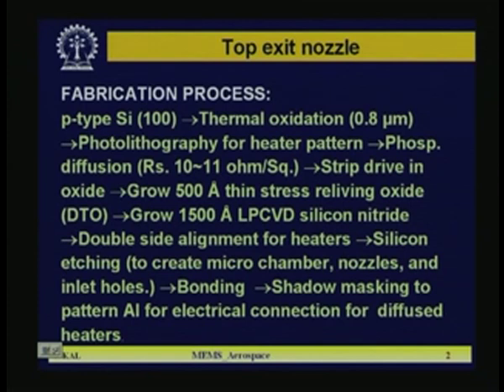to 10 to 11 ohm per square. Strip the drive-in oxide, grow 500 angstrom thin stress relieving oxide, DTO. That is the process which they followed, as reported in the literature. After that they grow 1500 angstrom LPCVD silicon nitride for insulation, do double side alignment for heaters, and silicon etching to create microchamber, nozzles and inlet holes. These are the three microstructures. One is the microchamber, another is the nozzle, and third is the inlet holes.